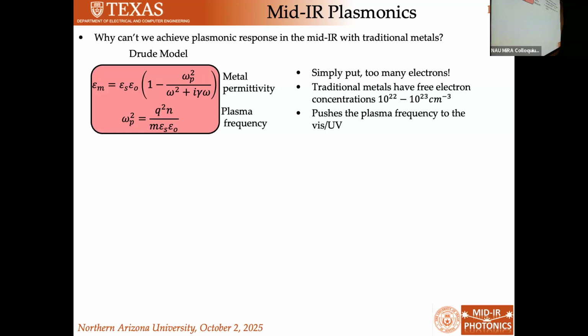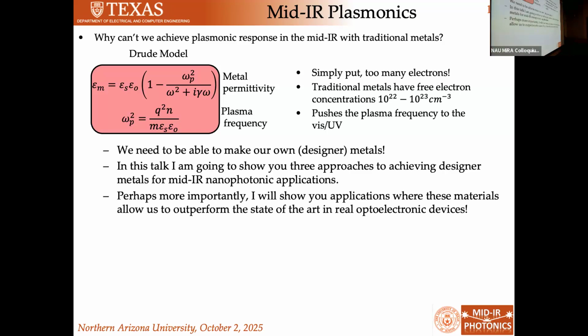And if you do this for a typical metal, what you'll see is that in the mid-infrared, the permittivity is quite large and negative. The reason for that is that your plasma frequency is too high. In other words, there are too many electrons. N is the number of electrons. Too many charges, right? In a metal like gold or silver, you have 10 to the 22nd, 10 to the 23rd free electrons sloshing around, and it pushes the plasma wavelength to the visible or UV.